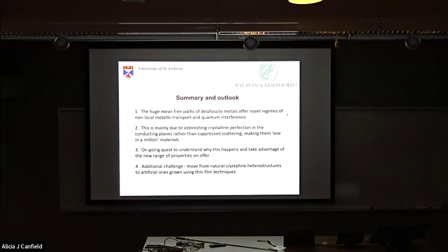So it's on the order of magnitude weaker than copper or silver? It's of order copper, or a very weakly electron-phonon coupled metal. But your room temperature mean free path is still much larger than in copper or silver. Yeah. So that must be several times, like an order of magnitude weaker. So how come? I don't know.